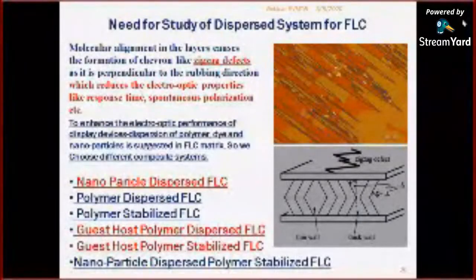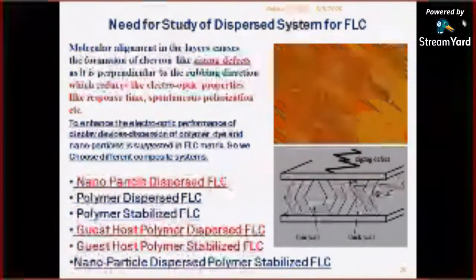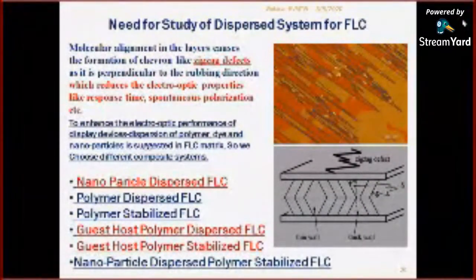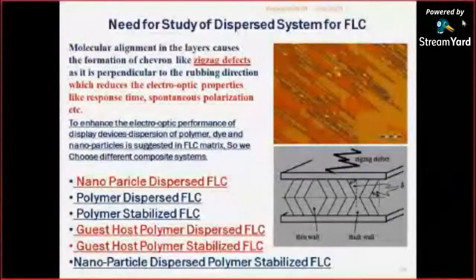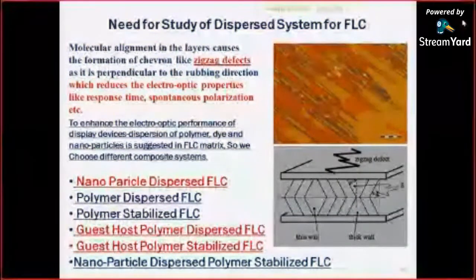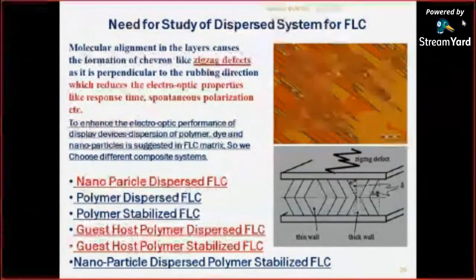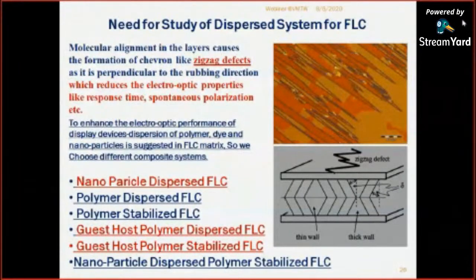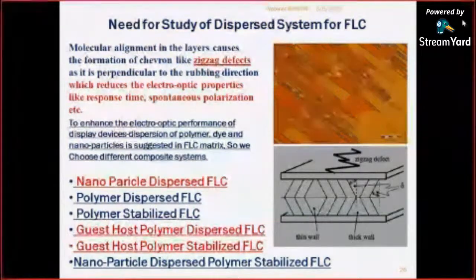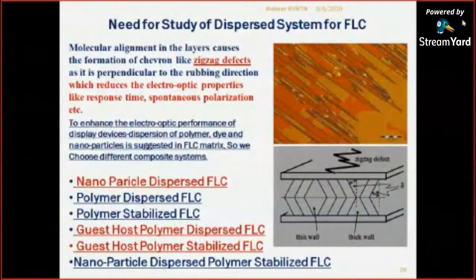So this is the main target: we want to increase the response of these ferroelectric liquid crystal displays, reduce the zigzag defect, and enhance the electro-optical property. This was the main reason to study the sample with nanomaterial, because liquid crystals have some kind of chevron-like defect structures. That defect has been stabilized by some kind of nanomaterial. So it is suggested that nanomaterial can improve the ferroelectric liquid crystal matrix. So we choose different types of nanomaterial to disperse in the ferroelectric liquid crystal.